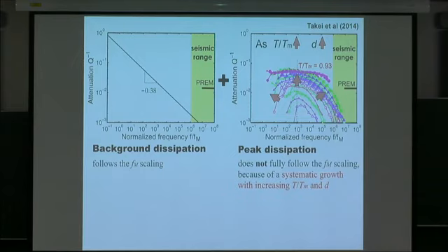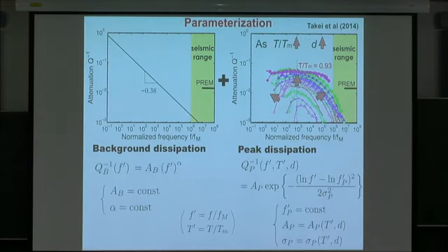And the highest homologous temperature of this data set is 0.93, which is lower than the solidus temperature. However, the peak is already broad and large, so this suggests that the seismic low velocity and high attenuation can occur below the solidus even without melt. And we consider this suggestion very important, and to apply our data to the mantle, we performed a parameterization of our result.